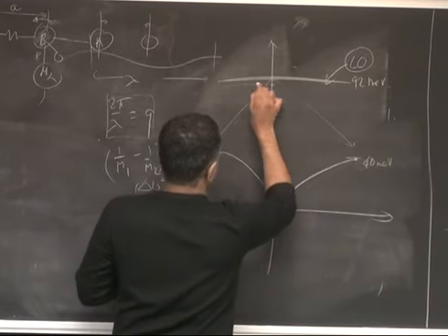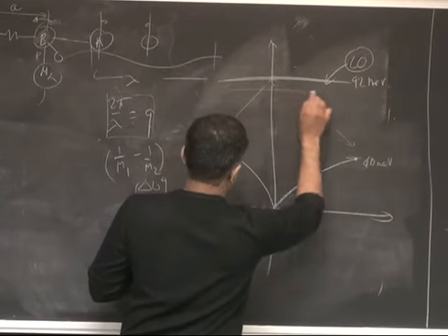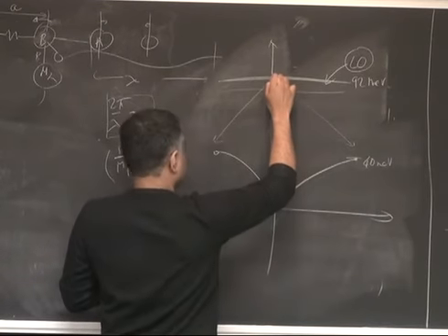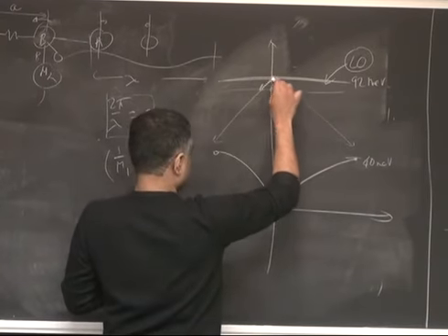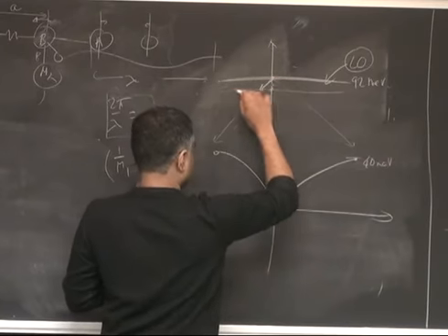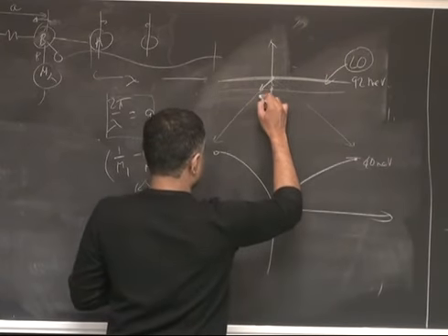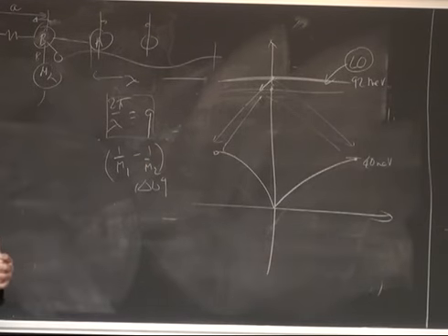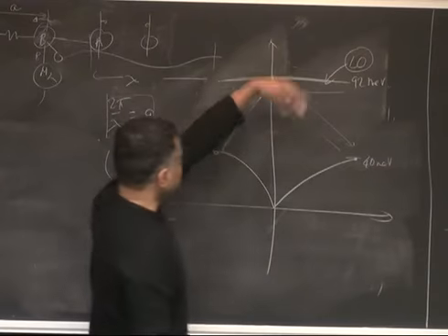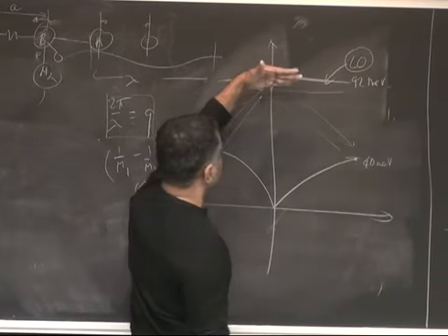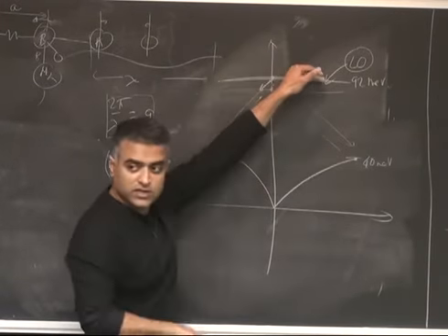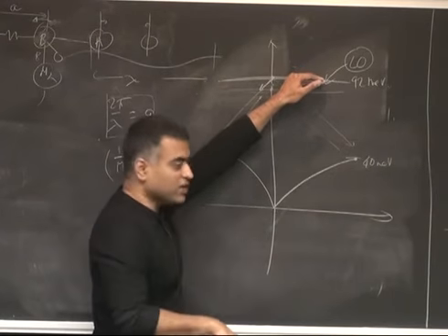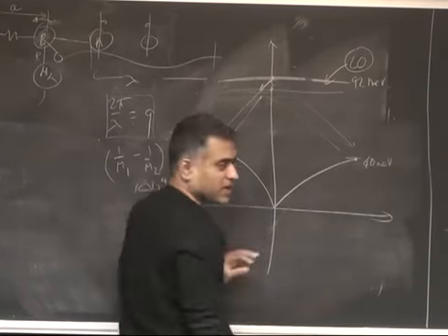So there are transverse optical modes here, which electrons don't couple to directly, but then they have to go through an even more inefficient process first. And then the transverse modes cascade down, and then you can finally get in there. So that process slows down the decay. There are examples like that. But what I'm saying is the energy from the electrons can be dumped very easily into the LO phonon modes. And whether the LO goes from here to there, that's the harder part.